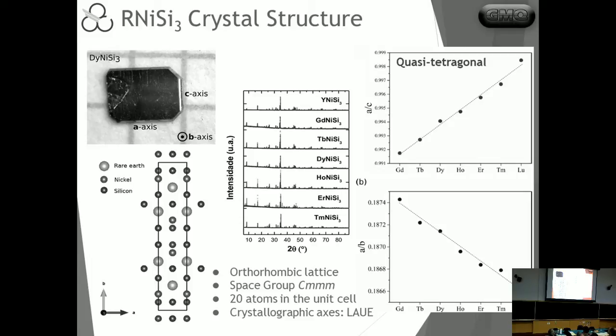What we see then is that they start out in gadolinium. It starts out reasonably orthorhombic. There's more or less 1% distortion here between A and C. But then as we move along the series towards Terbium, this really moves strongly into a quasi-tetragonal situation up here. So this is basically 0.1% distortion. So it's basically tetragonal system.